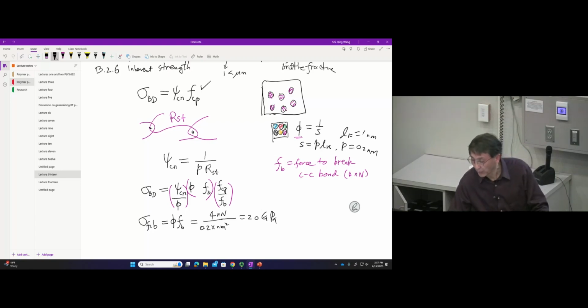The best fiber we can achieve industrially does reach something on the order of 10. So it's getting very close. It's actually reassuring that this estimate is good. Meaning we're off by a factor of 2. That's really quite impressive already. So that's the fiber limit. Let's look at